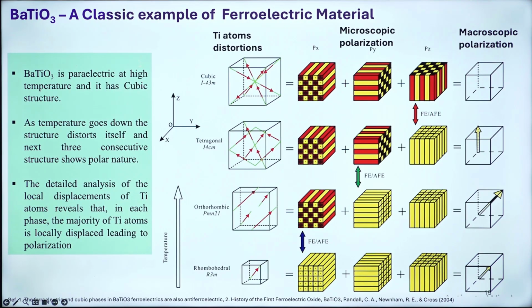So that triggers the ferroelectricity. This is bulk. As a bulk barium titanate, if you lower the temperature, it undergoes a temperature induced structural transformation from cubic to tetragonal to orthorhombic to rhombohedral, and you see cubic is paraelectric, so we don't see any polarization. As and when you lower the temperature, the structural distortion happens. This is a displacive transformation where we go from a paraelectric to ferroelectric structural transformation.